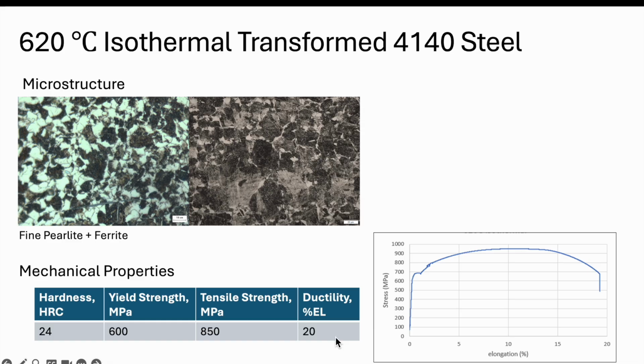So we're at about 20% elongation before fracture. So strength goes down, ductility goes up. We change to a yield point instead of the more gradual transition that we saw on the previous. And additionally, the hardness, the Rockwell C value, is 24. So we're going down in hardness as well.